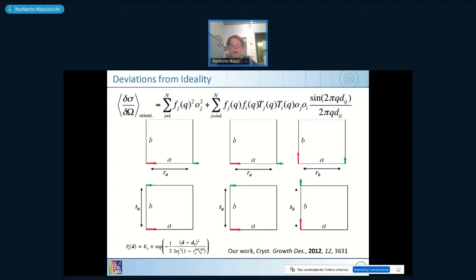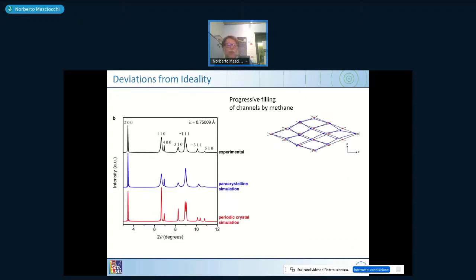So this is the original Debye scattering equation, coupled with this one makes the computation a little bit more complex. And if you do this simulation, the original periodic crystal simulation transforms into a paracrystal simulation, and now you can check that the experiment and the paracrystal simulation are very similar. That means that the paracrystal simulation picks up the features which are experimentally seen. But now that we have this paracrystal simulation, can we interpret it?